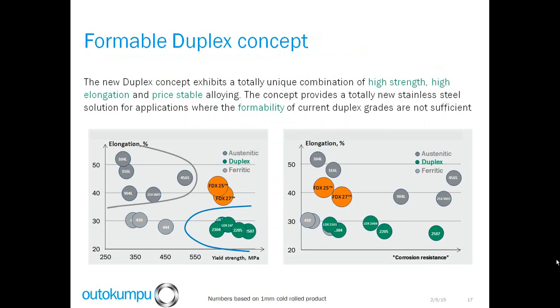This is a slide basically summarizing the formable duplex stainless steel concept. The figure on the left shows the new formable duplex grades FDX 25 and 27, and they have higher elongation compared to other duplex grades. The elongation is similar to that of the austenitic grades in this figure. If we look at the figure on the right, it shows that the corrosion resistance and elongation of FDX 25 and 27 are similar to that of 304 and 316L stainless steels.